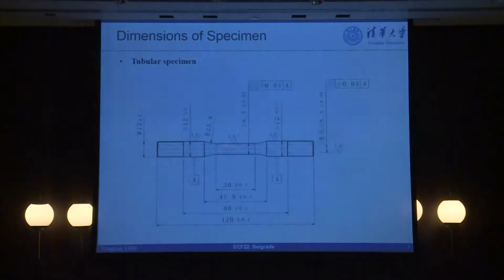That is the specimen we manufactured. The external diameter here is 12 millimeters. The thickness of the tubular specimen is 1 millimeter. The reason is that below 1 millimeter it becomes very sensitive to manufacturing, and in the real blade the thickness of the material is around 1 millimeter. Much less than 1 millimeter becomes difficult. The length is 120 millimeters. That is the specimen.